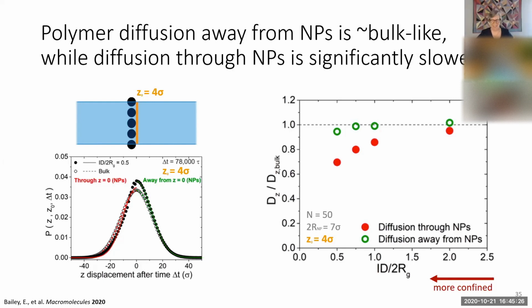So the polymers in the really confined cylinder were like plugs, you said? Between the two sheets, do they form tiles but can still diffuse relatively quickly? To the extent of, we actually looked for that very carefully. We looked for the propensity that you would find a bead from your same chain as opposed to a bead from another chain, so kind of like your self environment. And as we get more and more confined, there is a slight tendency towards that segregation, but it's slight.